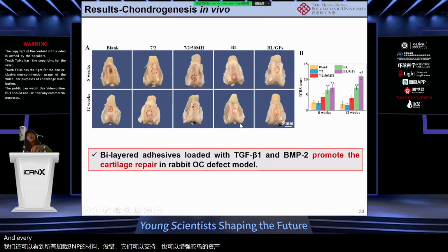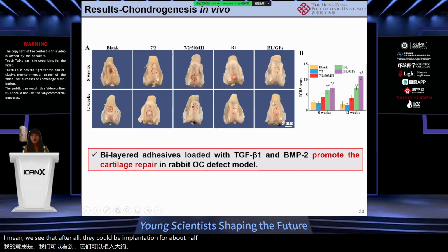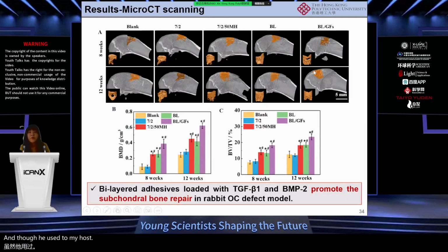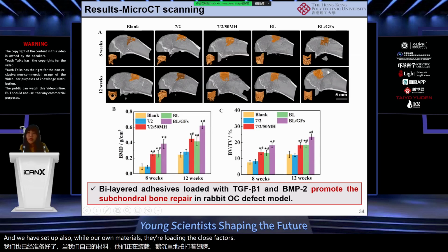And then we inject these materials into the rabbit femoral condyle. And we see that after implantation for about 12 weeks, the cartilage can be nicely regenerated. And then we use the micro CT to examine the bone regeneration. And we can see that also when our materials are loading the growth factors, they can have a really nice formation of the bone.